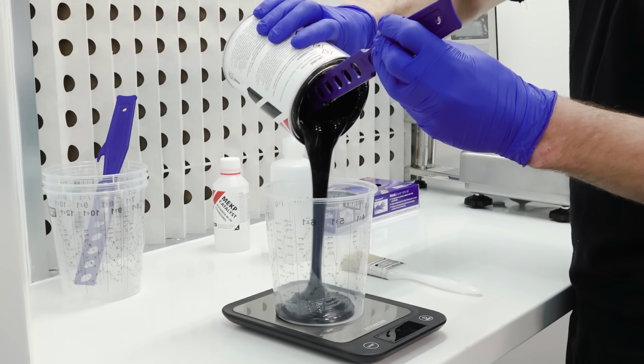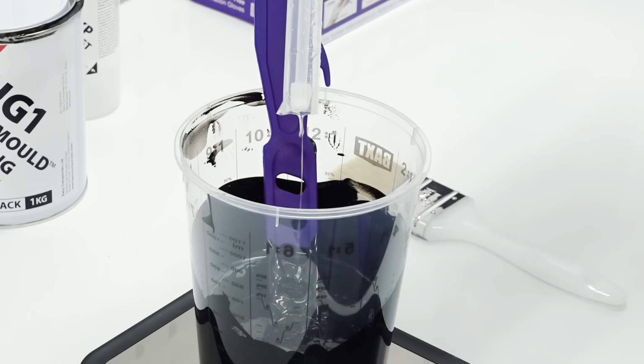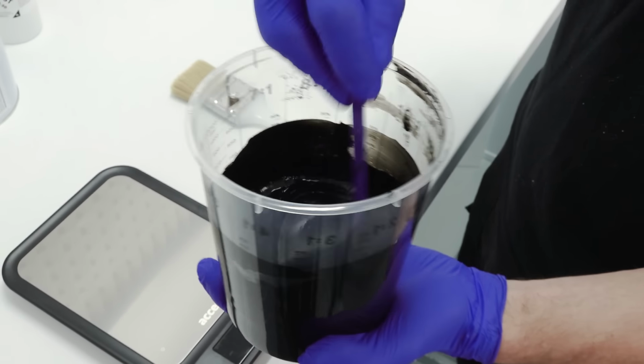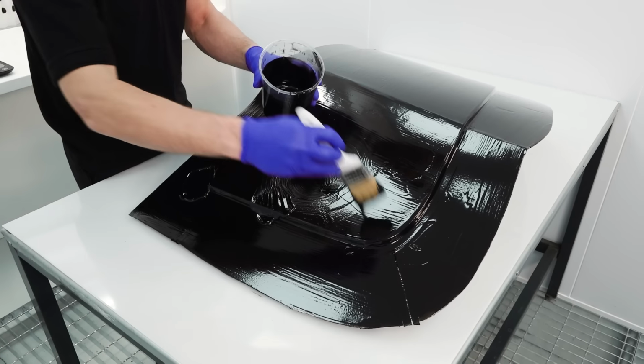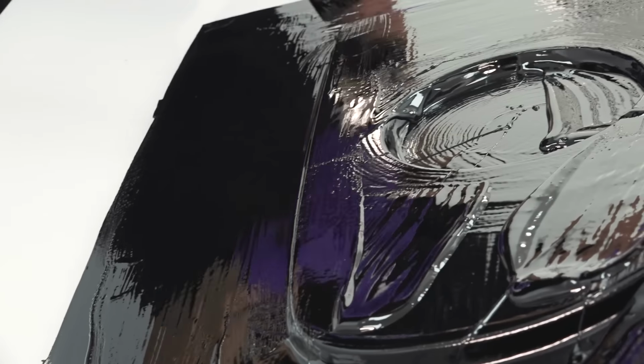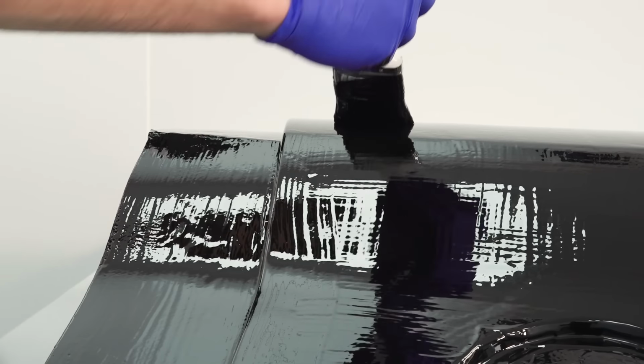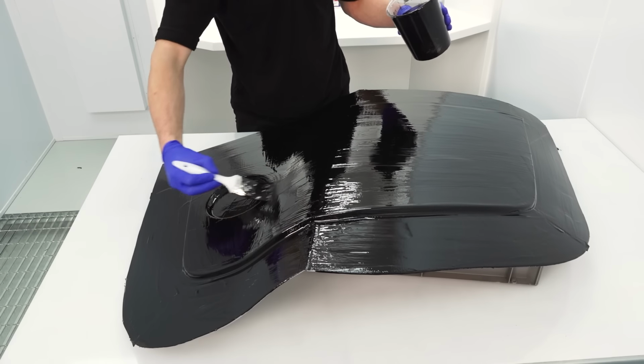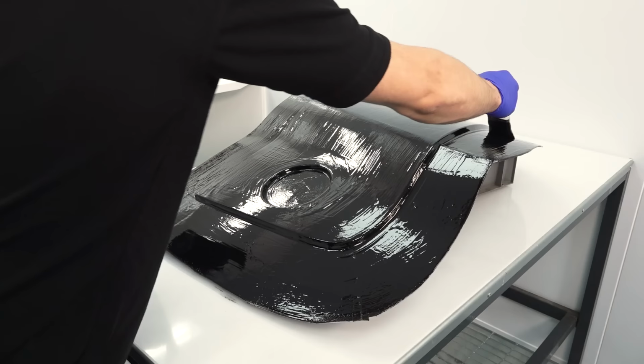With the first gel cured, I'm now applying a second application in exactly the same way as the first. On simple flat moulds, a second gel is not necessarily required, but in most cases it is a good idea as it will ensure that you have a good thickness of gel everywhere, which is going to reduce the print through and allow for more flatting and finishing on the mould. Again, this second coat is allowed at least 4 to 8 hours to cure solid.